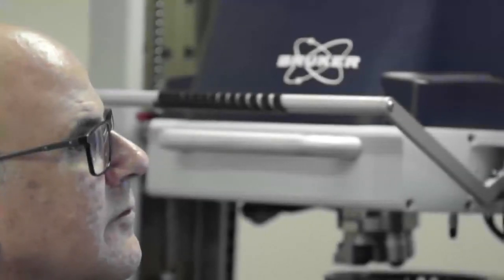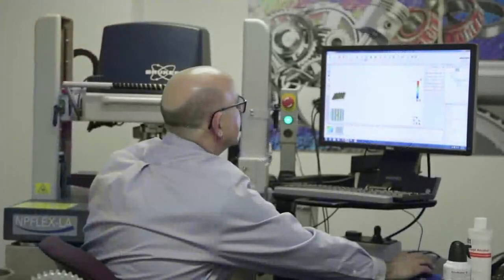So once you've narrowed it down to the interacting components, now it's a question of, okay, can I position the parts in such a way that I can measure them, looking for the surface texture differences between them. And for the most part, the instrumentation we have from Bruker can handle pretty much any material. It could be highly reflecting, it could be dull finish. I can measure black rubber surfaces with a little bit of patience, and you can get a really good measurement of that surface texture. So usually most materials we can measure.